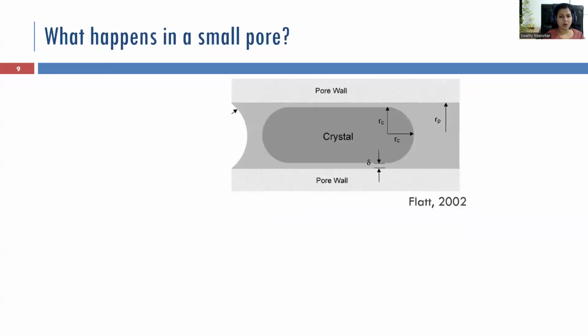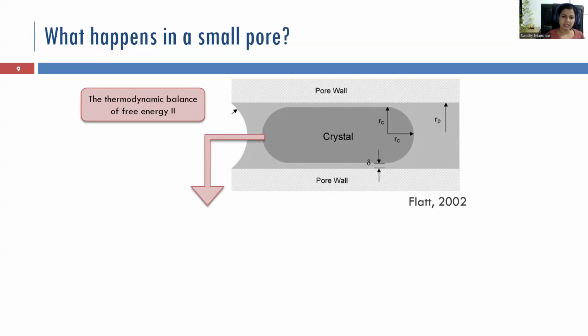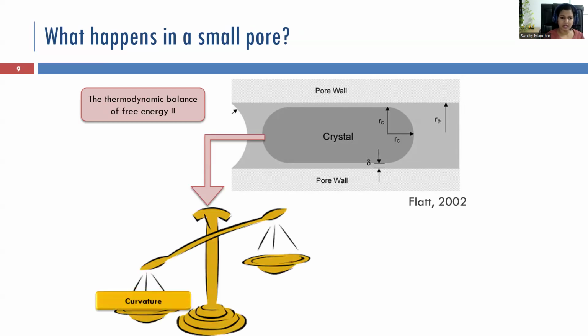This is not the case in a smaller pore. Here you are seeing a smaller cylindrical pore with pore walls on the sides and the crystal being stabilized inside. The crystallization pressure will arise here based on the thermodynamic balance of Gibbs free energy. I want you to look at the crystals first at this end. The ends of the crystal have a hemispherical shape, hence the curvature is very large there. The solution touching that curvature should have a very high supersaturation to balance the free energy there.